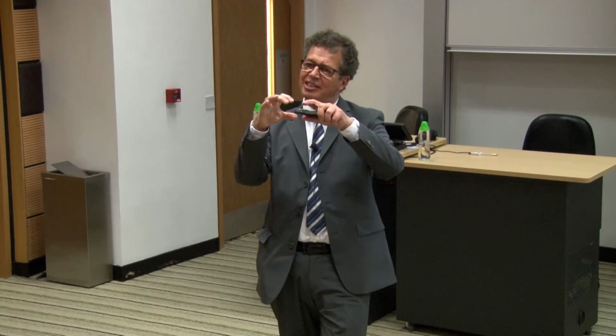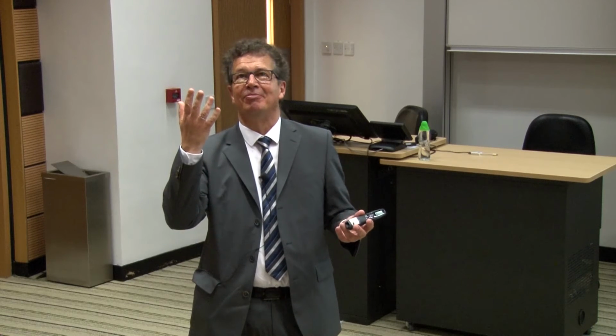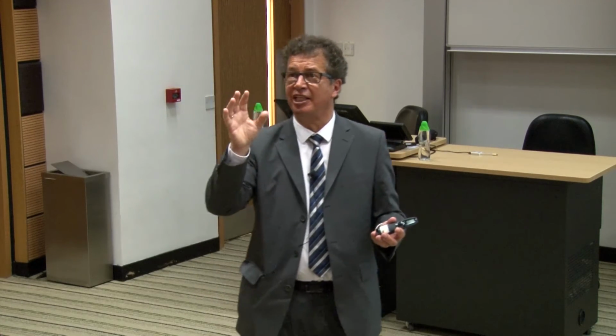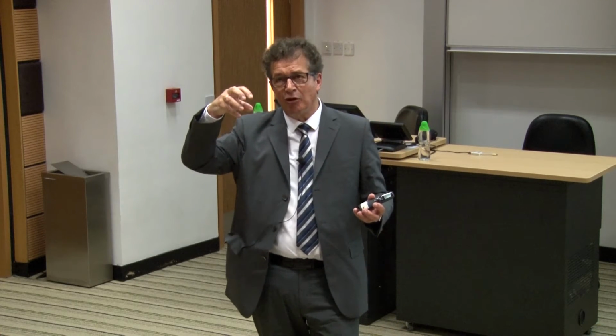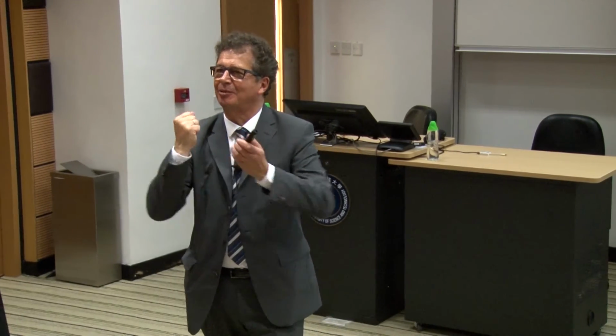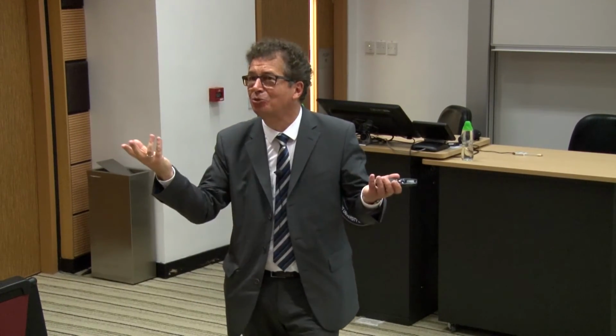Why this? I think I have an idea why the self-assembly is occurring in such a way that you really form single crystal nanowires. I think really this is an energetic process, and this is a minimum energy rather than having the single crystals oriented in different ways. I think this answers this question, but why they do it in the first place, why they don't stay separate, because from an electrostatic point of view, they should stay separated because we're talking about nanoparticles with a lot of positive charges on the surface. So kinetically, they don't like to get together because they have the positive charges on the surface, yet they do this for whatever reason. I would be happy to know this.